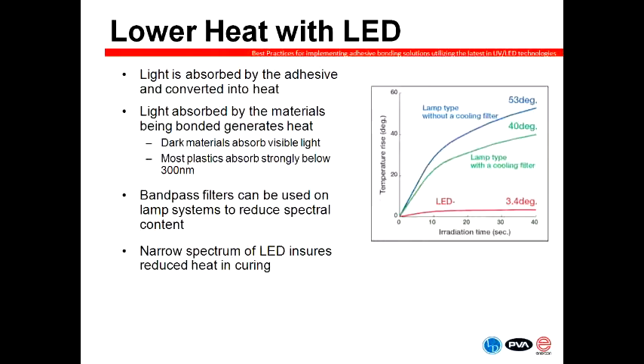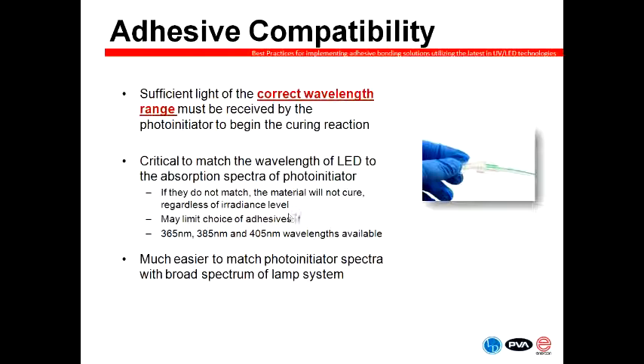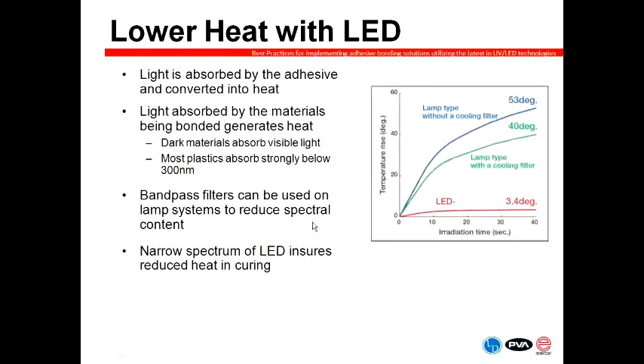on the flip side of that, the real benefit of the LED is that because you're using that very narrow spectrum of light, you are able to minimize the heat that is being generated during the curing process, because you're being very specific on the wavelengths of light to the requirements of the photoinitiator. Now, in a curing reaction, you have light that's being absorbed by the adhesive, but you also have light that can be absorbed by the parts. And things like dark or colored materials will often absorb visible light, and many plastics will absorb light below 300 nanometers, for example, depending on the plastic being used.